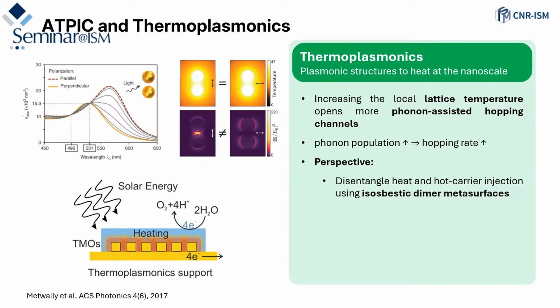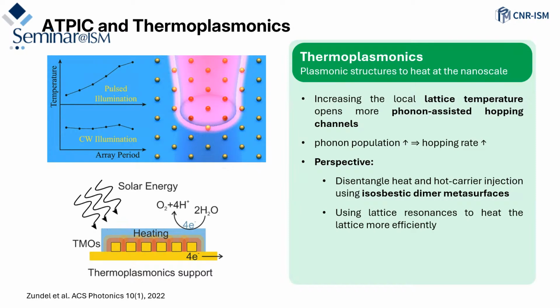And also we can have, for example, charge transfer. So if we have to be very, very precise, it is a thermal effect that enhances the mobility. We also should disentangle those effects. On the other side, it is also reported in the literature that lattice resonances, so the distribution of some nanoparticles and some nano units of plasmonic structures, can be more efficient in terms of quantity of scattered and also absorbed light per unit area. So those systems should be very nice for this kind of application.